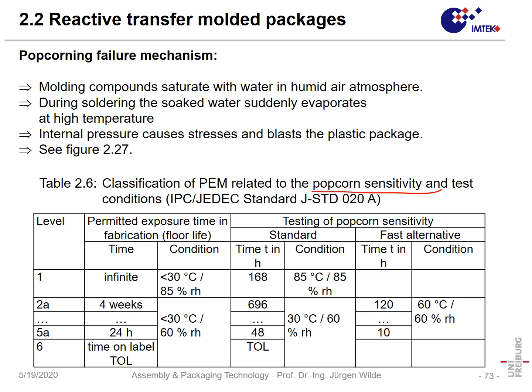If you have other conditions, for instance, below 30 degrees centigrade, but in a quite normal atmosphere, 60% relative humidity, that could be here a non-climatized lab in Europe. And if you can keep it for 4 weeks, then it's level 2A, and there are intermediate levels. If you can keep it only 24 hours under these conditions, then it's level 5A, which is a relatively bad level. What's the idea behind this? Typically, manufacturing machines for pick and place, they are loaded from a magazine, and often standard devices stay in that magazine overnight. Yeah, for instance, a certain microcontroller or some logic IC.